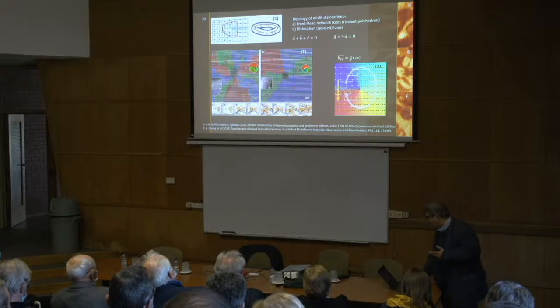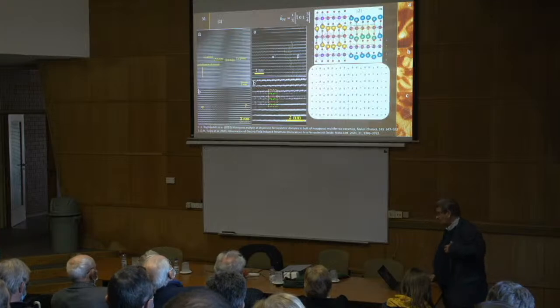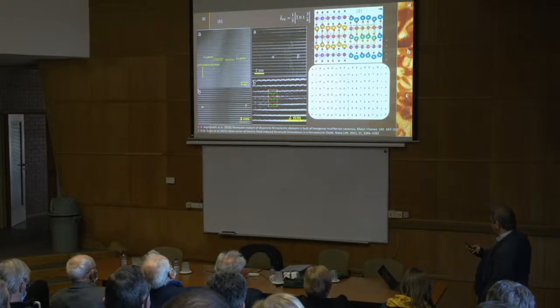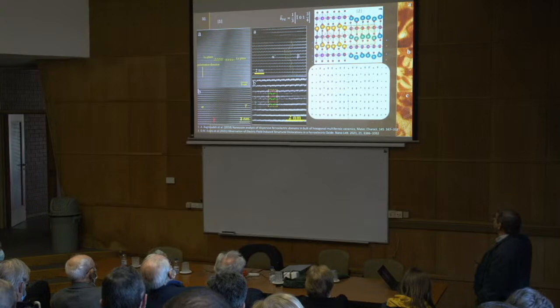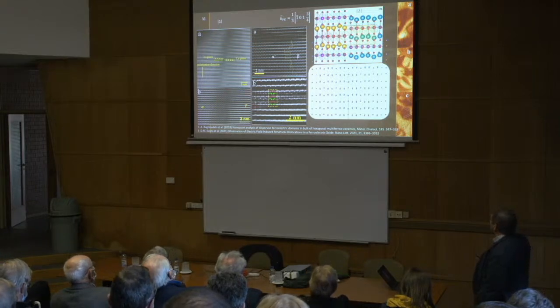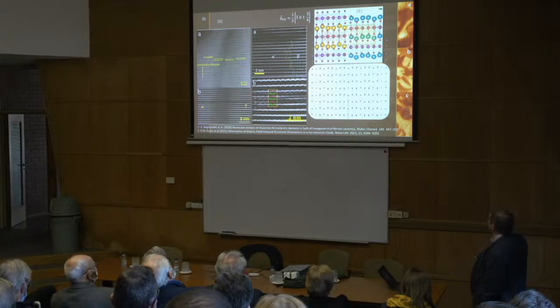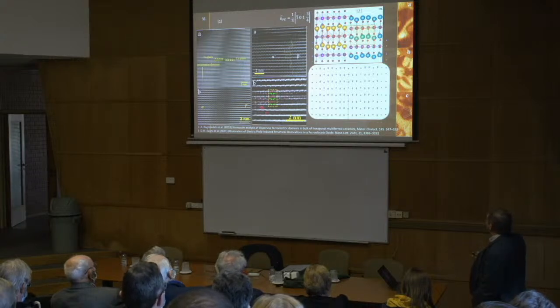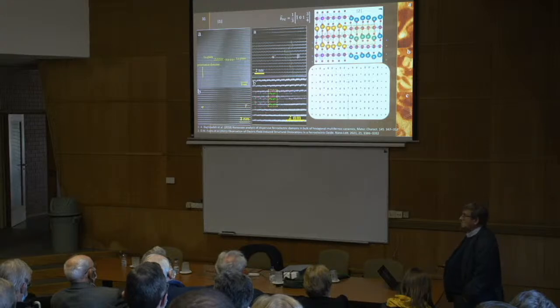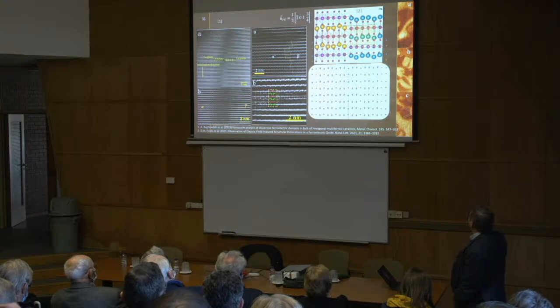And why bring it up? Because we have been investigating also these dislocations for technological reasons. We found a very strange dislocation. Can you see how this dislocation, this is a stacking fault created by a partial dislocation. The atoms are more or less looking face to face, face to face. The lattice does not have this feature. They should be up or down. Very recently, even as I was reading it, I said, this is our dislocation.